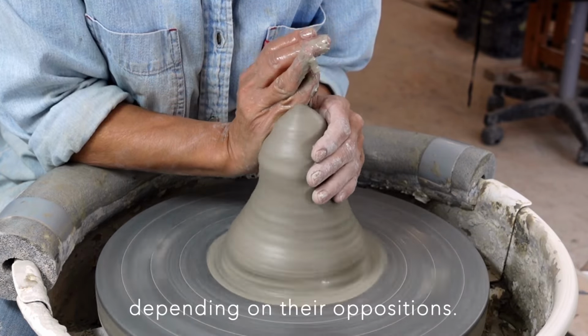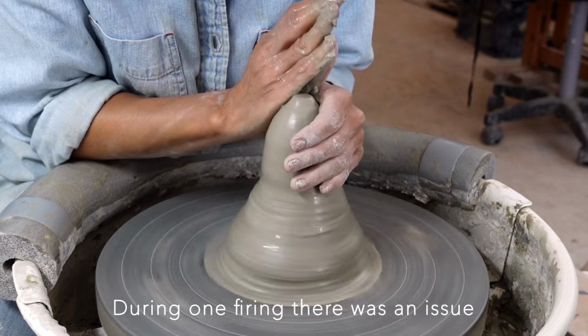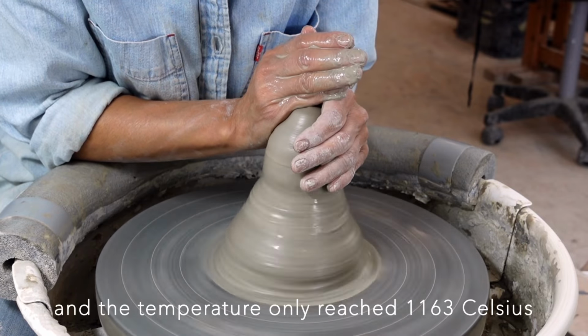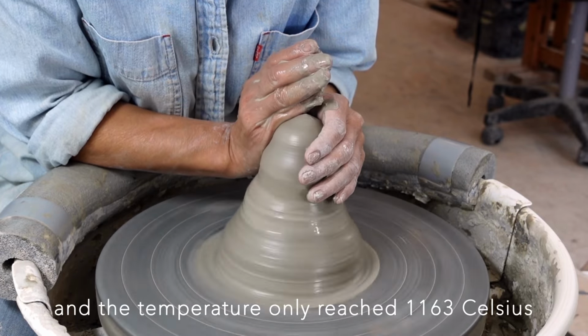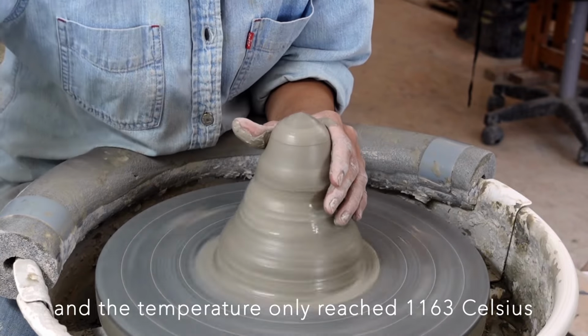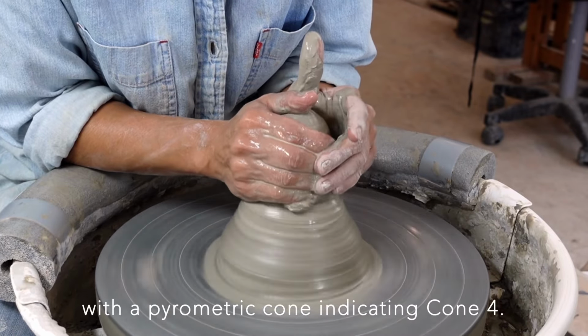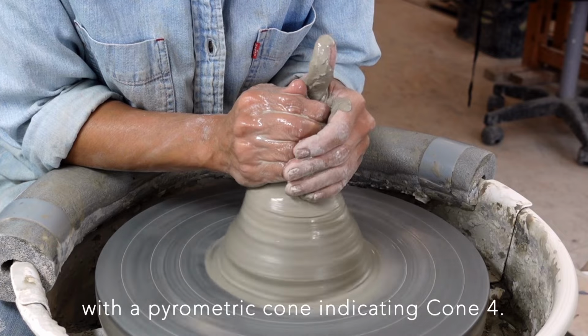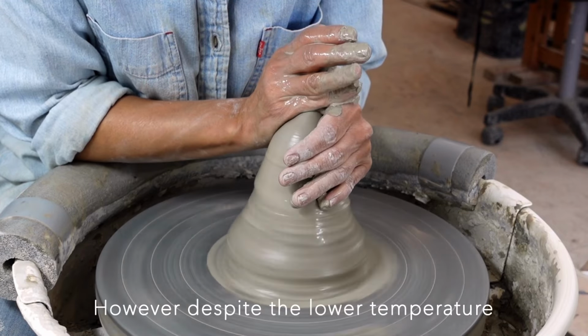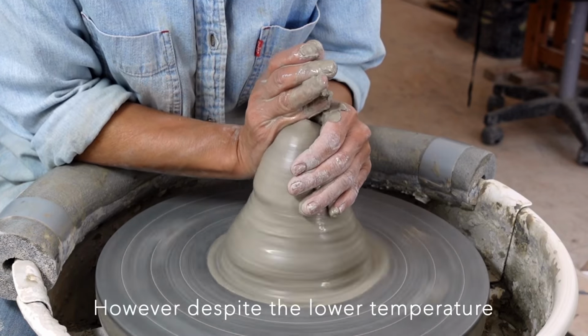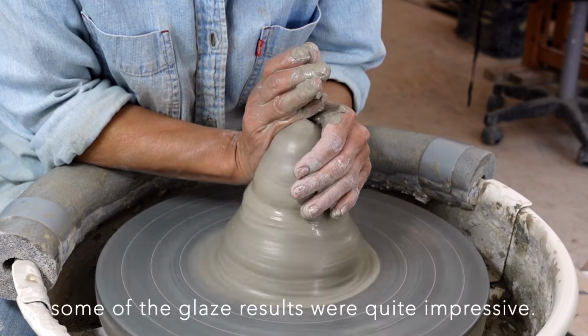During one firing, there was an issue, and the temperature only reached 1163 Celsius, with the pyrometric cone indicating cone 4. However, despite the lower temperature, some of the glaze results were quite impressive.